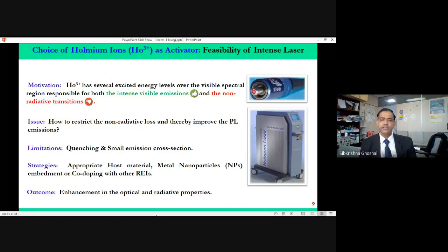The problem is that the intense visible emission is okay, but the non-radiative transition is too high. Because if the non-radiative transition is high, it means phonons will eat the photons. So phonons are the enemy of the photons, and photons from the material will not come out. How we can eliminate the effects of phonons, which are responsible for the non-radiative decay, is one of the challenges in these materials. What are the limitations? The limitations are basically the quenching and small emission cross-sections. So intensity quenches because of the non-radiative transition, and also the emission cross-section of the rare earth is already low, and that's where the improvement is needed.